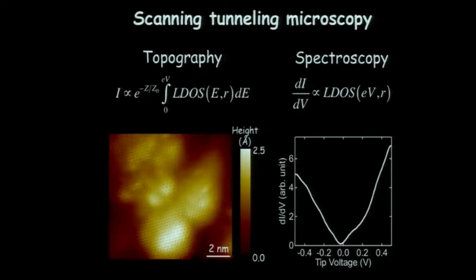But what you can see is it doesn't only depend on this e to the minus z over z naught. There's also this integral over the density of states of the sample, so there's also information about the electronic properties of the sample. The way we isolate that is, instead of scanning our tip over the sample, we go to a fixed location in the sample. We turn off the feedback circuit that we're using to keep the tip current constant, but we keep the tip height constant, and we measure the changes in current as we change this voltage here.